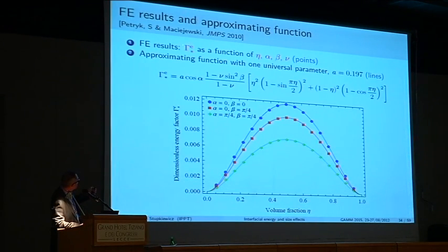So to compute this, we use the finite element method, and on this plot you see the dots. These are the results of the finite element simulations for some selected parameters. So this is the volume fraction, and then the geometrical parameters alpha and beta. And the solid lines are an approximation function, which we happened to find quite a good approximation, as you can see, with respect to all four parameters involved. And the dependence on eta is here, and the dependence on alpha is just by cosine. This is just geometry, and this is related. This we take from the dislocation theory. We have guessed the dependence on beta and nu, the Poisson's ratio.